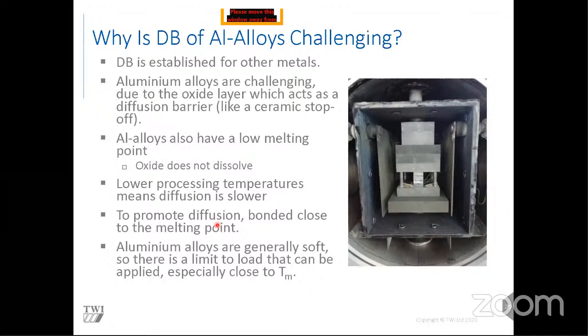How do you decide the load and temperature? Good question. A lot of this is a combination of looking at what exists in the prior literature and prior art, and also consideration of the alloy itself - they'll have a certain solidus and liquidus. Certain alloys will have a phase change, such as titanium, so you try to avoid the alpha beta transition temperature, for example. So it all depends on your material, but ultimately we carry out small scale trials - it's an iterative process. You'll probably need between 5 and 10 samples to narrow down your processing parameters before going to a larger scale.